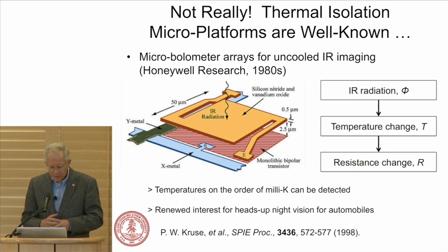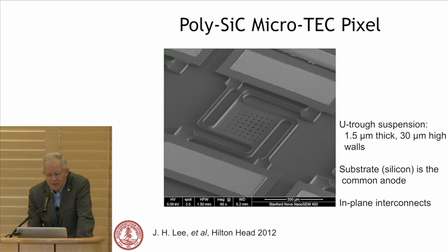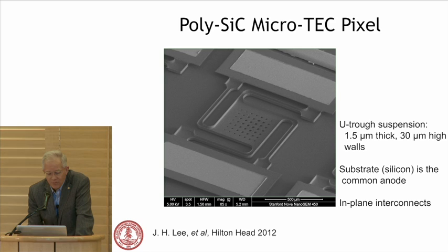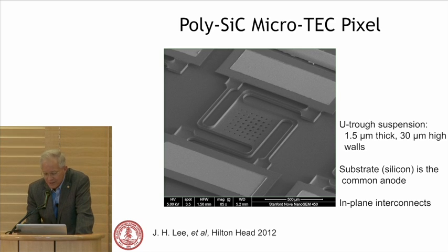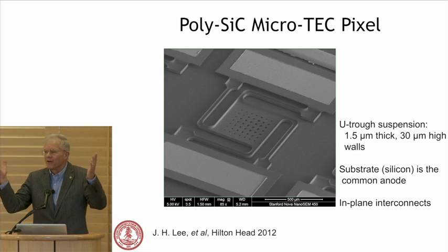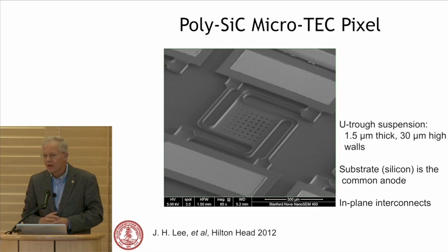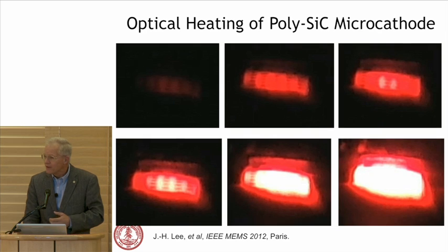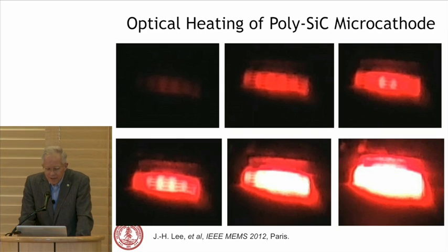And in fact, these are fabricated using the kind of micromachining technologies that would be the subject of basic grad courses at Stanford. In fact, we've applied that technology to make a suspended structure out of silicon carbide with no tungsten, no work function coating, just as an existence proof. And in fact, we ran it as a converter using the silicon substrate as the anode. What would the converter look like on the Ivanpah Tower? Massive arrays of pixels, possibly individually addressable. EEs like that idea. We can do some interesting things with access at that level. So actually, optical heating of this, we don't have any problem going incandescent and keeping the substrate quite cool. And so thermal isolation in a vacuum is a non-issue.